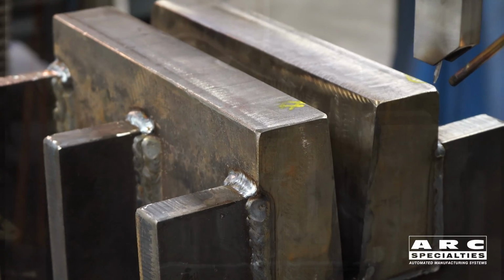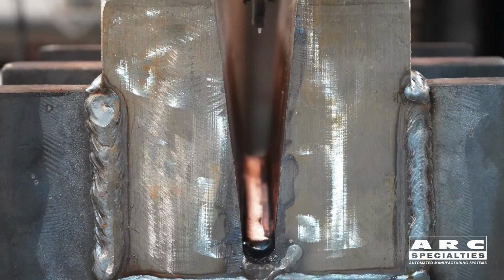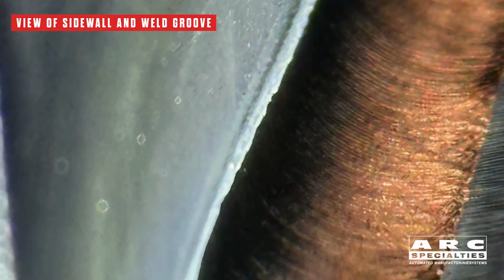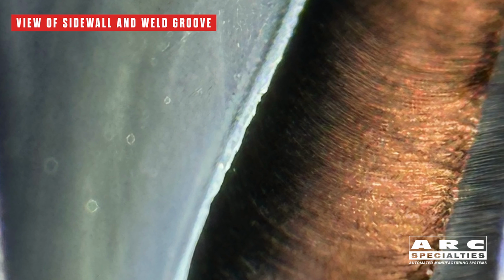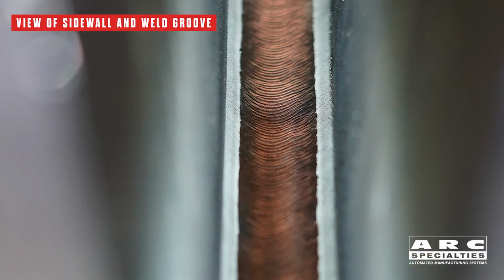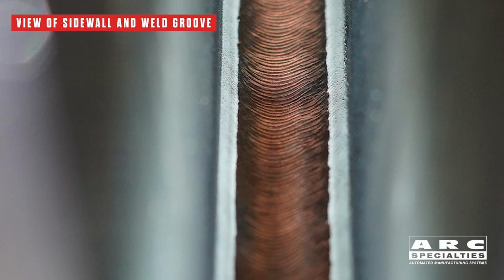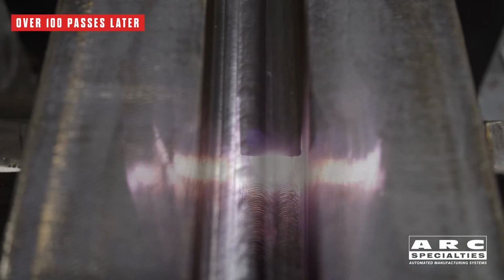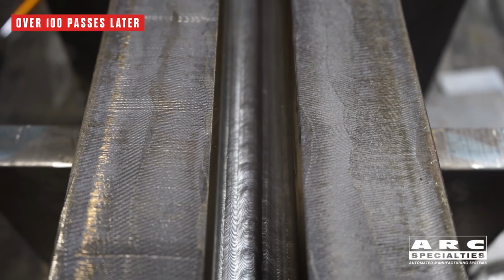for your joints. We have three different welding technologies that we might apply: gas tungsten arc welding with hot wire, we have submerged arc welding, as well as gas metal arc welding. Particularly on thicker joints, you might see a reduction in weld volume and weld time on the order of 80%. If this might benefit you, give us a call.